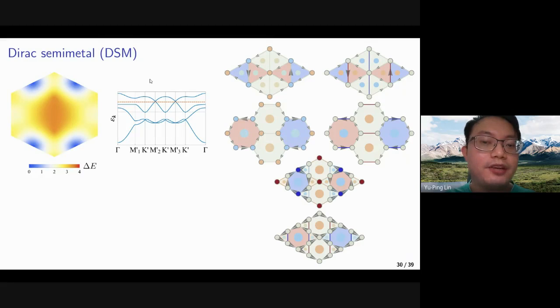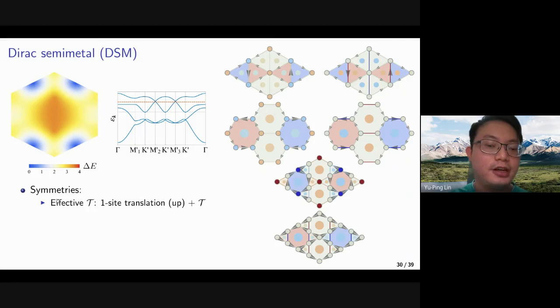So because we have different kinds of gapped phases, we should also have some gapless phases in between. So the first kind is the Dirac semimetal, where you can see that if we introduce some kind of orders, there could be 2 Dirac points in the band structure, equivalently at least 2 points. And on the lattice, we will have some site and current orders. So the symmetries here are as follows. First, we will have an effective time reversal. That is, if we apply a one-site translation upwards, we translate this bond to here, equivalently here, and apply a time reversal so that the current direction is reversed. We will return to the original pattern, so it is symmetric.